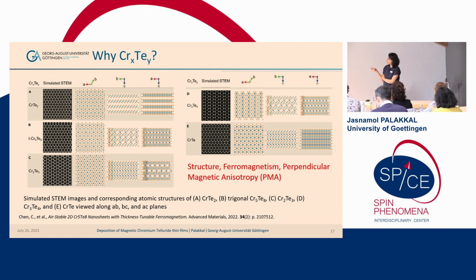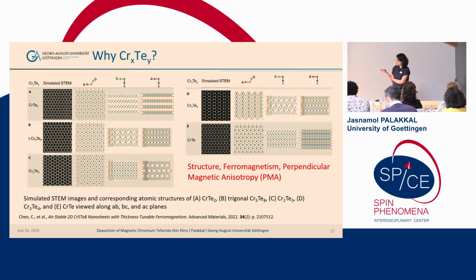And the question, why chromium telluride? As I said, it is magnetic, but depending upon this X and Y, they are showing different crystal structures. So it's quite a lot of possible structures. There can be 1:2, 5:8, 2:3, 3:4, 1:1. All these structures are possible, and all these structures are showing ferromagnetism. Some are showing ferromagnetism at room temperature and a huge perpendicular magnetic anisotropy.